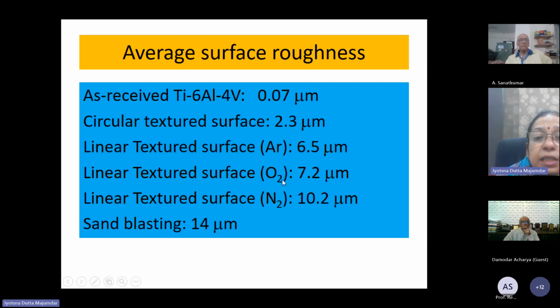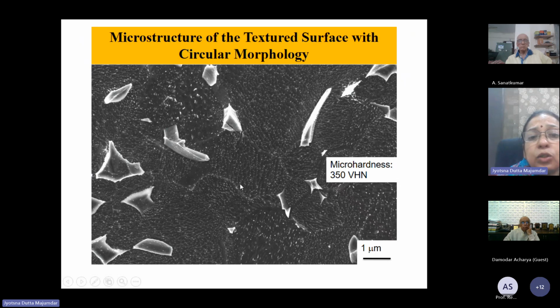We also changed the environment. In one case we used argon, in another case oxygen, along with laser treatment, and in the third case we used nitrogen. And our standard was a sand blasted sample. The sand blasted sample was also done in order to understand the effect, or added advantage, of periodic texturing over sand blasting. The textured surface, if seen at a very high magnification, was textured in air.